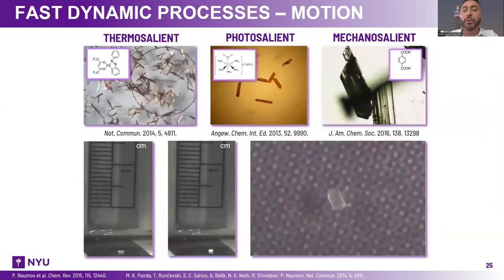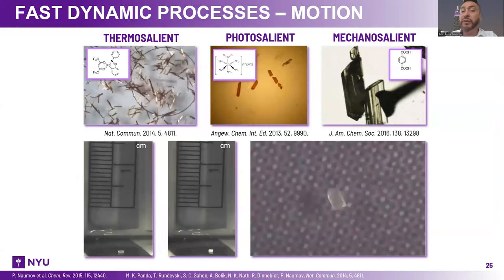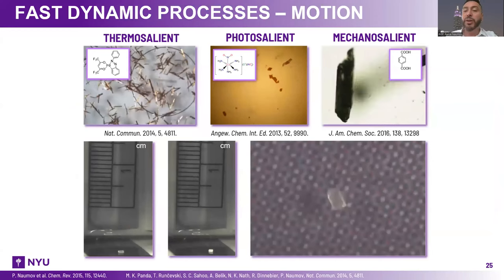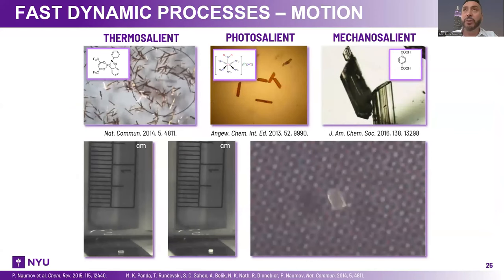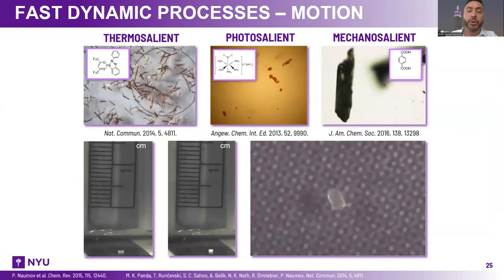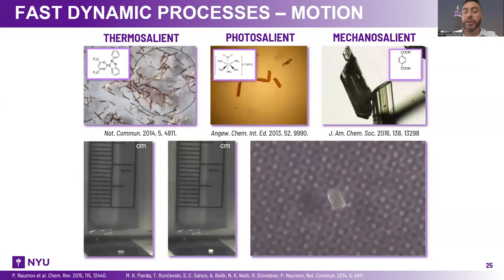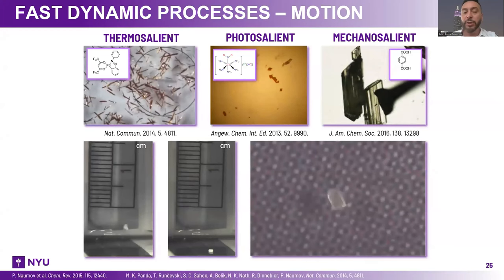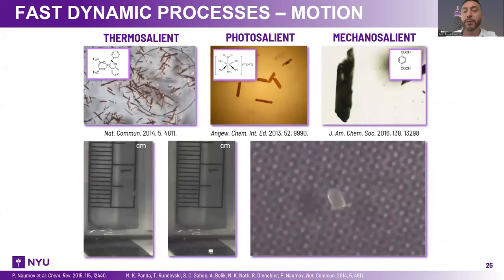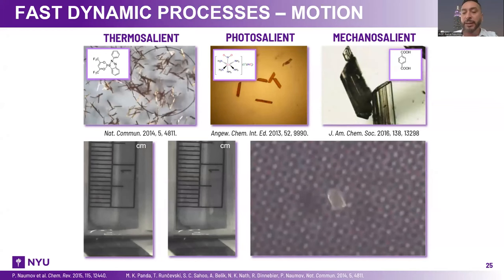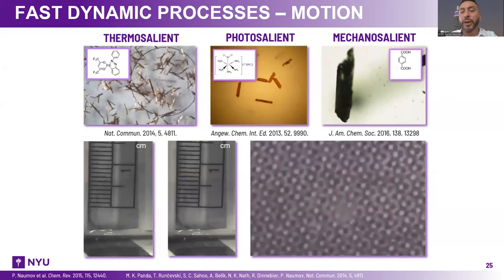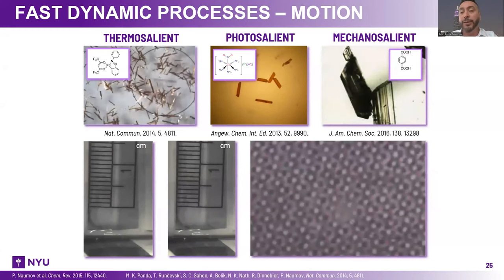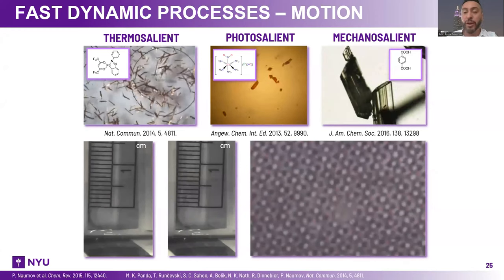A long time ago, about 10 years ago, we started to study also the fast phenomena, which are very important because in this case, you have a release of the mechanical energy on a very fast scale. And these are so-called thermosalient, photosalient, and mechanosalient crystals. They are so fast that we have difficulties to capture them with ordinary cameras, so we have to use a high-speed camera for that. And the interesting point here is that they are probably the fastest ways to convert thermal or photo energy into mechanical work.